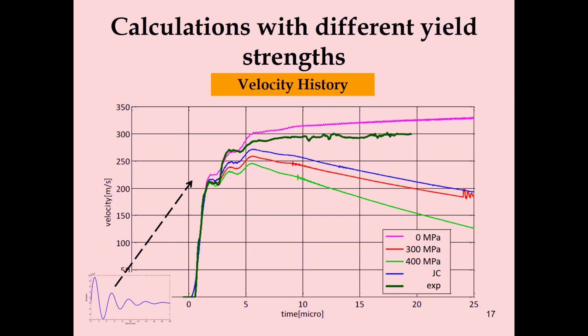And we could see actually, and I'll show you the two cases, the pink one here on the top would be without any strength at all, and the green one would be with, let's say, 400 megapascals. And you could see that the inclination is strongly related to the strength of the material in the cylinder. And this is the main point we should point out.